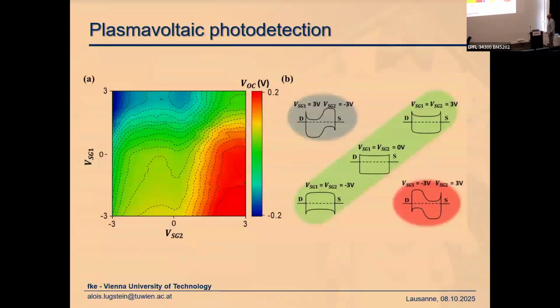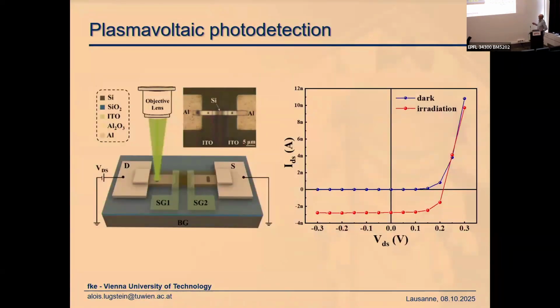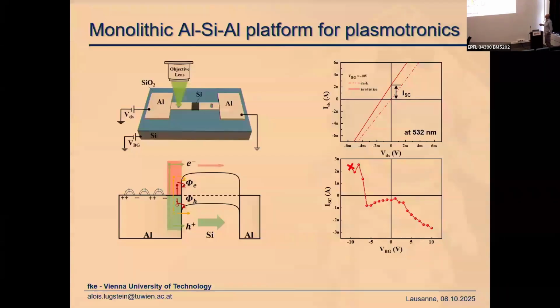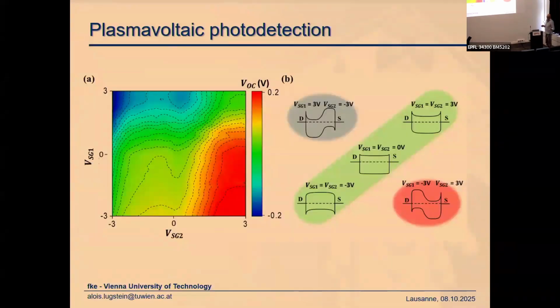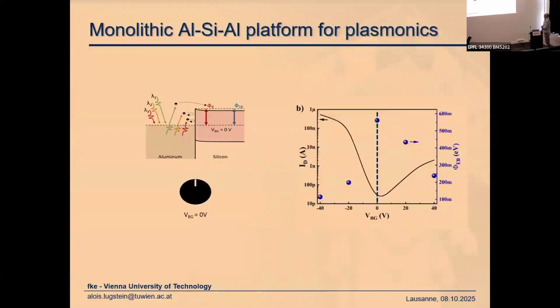And now you can play around with the backgate voltages, and you can really control if you inject holes or electrons. If you apply the same voltage on both electrodes, you have more or less flat band conditions. Here you inject the same amount of electrons and holes, and you get no current because the electrons compensate the holes.